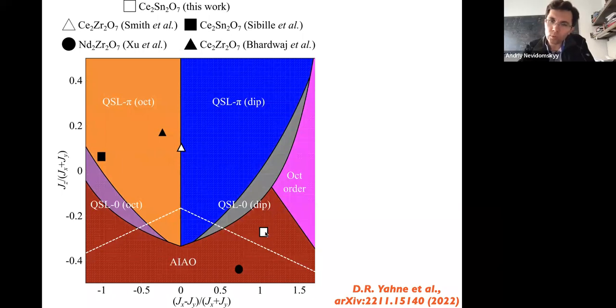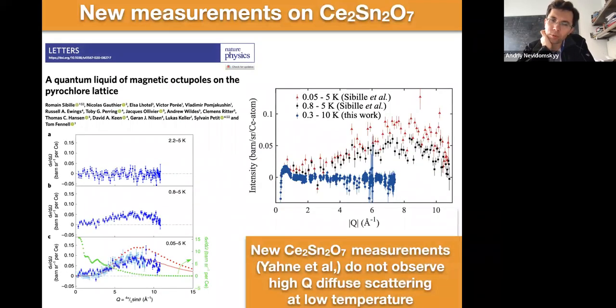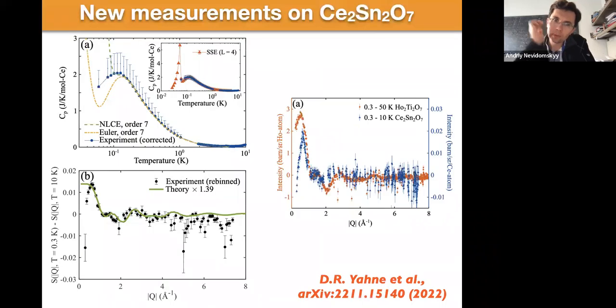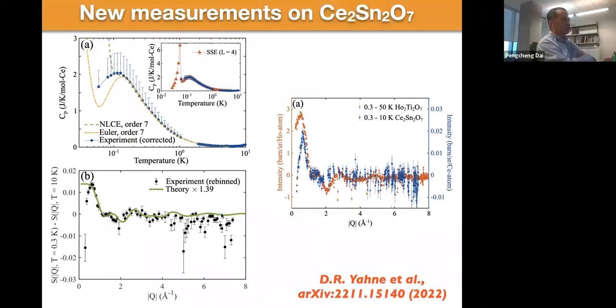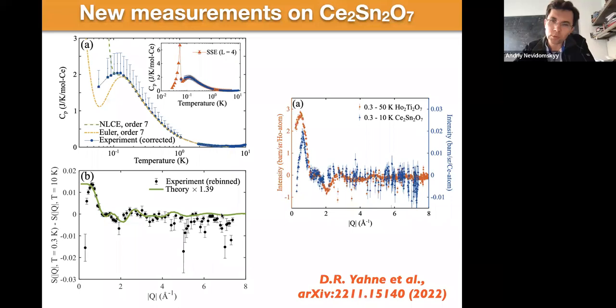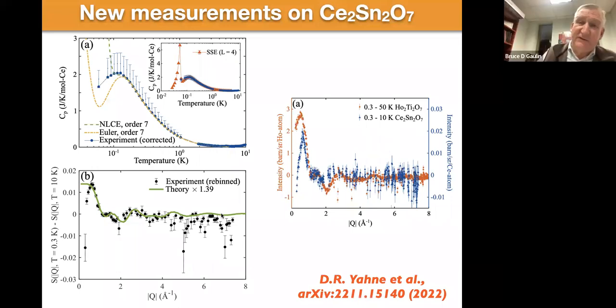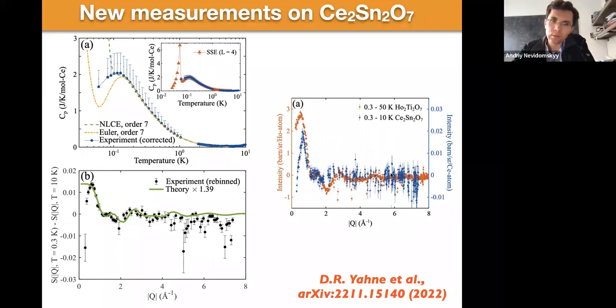Oh, this was low Q? Because I thought what Benedict fitted, didn't you have the plot? Yes, the low Q data, right there. But that's low Q data. 8 angstrom inverse is still low in this language? No, well, no. So this is the low Q. I mean, this is the conventional magnetic scattering, if you like. This is the magnetic scattering that looks like holmium titanate, right? I see. So you're saying that the fitting up to about 2 angstrom inverse is what sets those parameters, right?